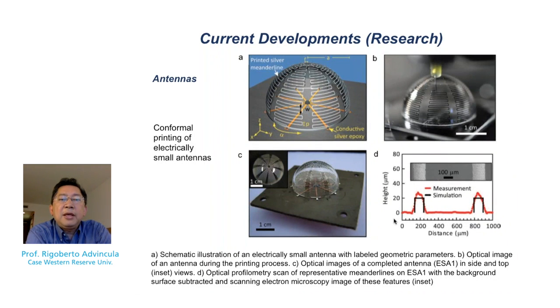However, the possibility of 3D printing on a curvilinear object or conformal printing on, let's say, a 3D printed object has been demonstrated. That means that you can 3D print, let's say, this antenna, or have basically a molded object, but then be able to deliver the conductive silver epoxy in a surface printing process resulting in this antenna. Now, the design of the antenna, of course, has to do with geometry and surface, as well as the active component that is used. It means that it is possible to use various types of designs or 3D printed object designs, and then on that object, deposit as a last step your conductive ink, or develop your antenna as a last step in the production process.